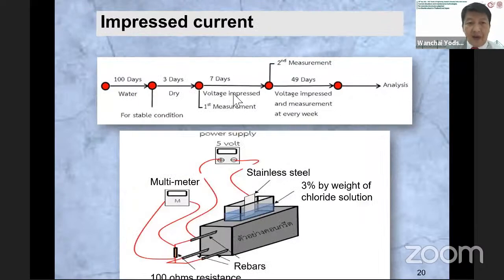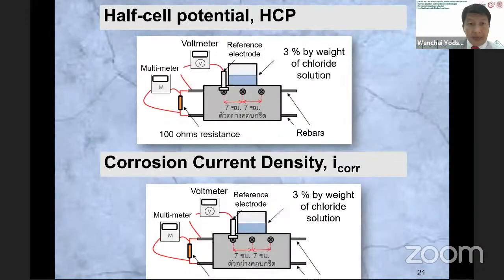For the impressed current method, we cure the concrete for 100 days and dry 3 days. After that, we have the first measurement, and we apply the impressed voltage continuously for 7 days, and then the second measurement here. And after that, every week, every 7 days, we have the measurement of the corrosion current and the corrosion voltage. And we measure the half-cell potential at 3 points at the side of the specimen like this one. And for the corrosion current, we measure the voltage across the 100 ohm resistance. And after that, we calculate the corrosion current.